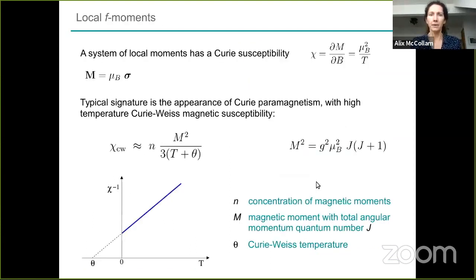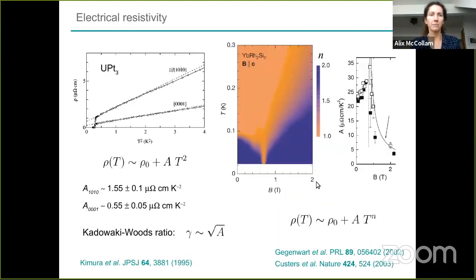Okay, so why do we have these particular experimental dependencies? So these are characteristics. They're common across many heavy fermion systems. And in many cases, you can continue them in high magnetic field, right? So you can do magnetoresistance measurements, or all of these things are things that we can measure relatively easily in high magnetic field. You can also do the quantum oscillation measurements, which I didn't show here because, well, you can't actually see what the behavior of the effective mass looks like there, but it's easily measurable when you measure the temperature dependence that I showed earlier.